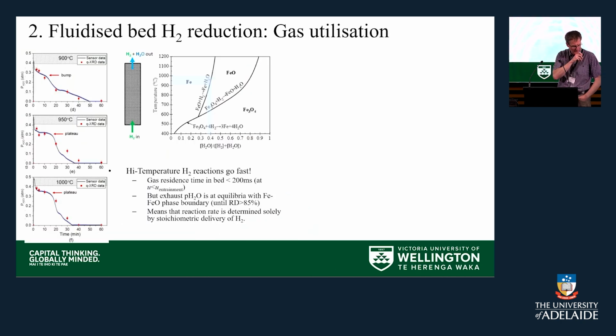So just to move quickly on the other thing, one of the other things we find in our fluidized bed reactor is that at these higher temperatures, when we're doing a batch reaction, we run and we hit a stable water output. And that's because we are running at this boundary, the iron-Wüstite phase boundary. So we've effectively hit thermodynamic equilibrium, even though we're running in a little test reactor that's only about 40 millimeters worth of bed height and has got a gas residence time of a few hundred milliseconds. That is enough for us to get to the gas equilibrium in the system.